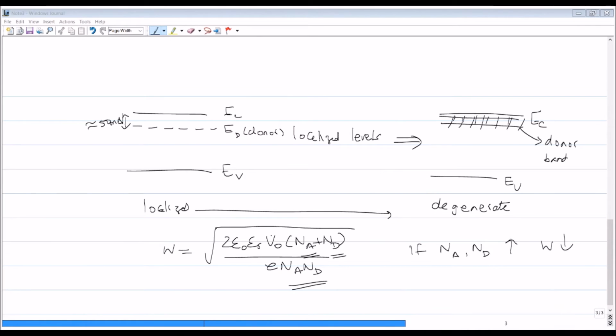Now to this semiconductor, let me add some dopants, let me add some donors. These are n-type. So we started off with p-type and now we are adding n-type, and this concentration is 5 times 10 to the 15. So it is more than Na. In this particular example, I have both acceptors and donors, so this is an example of compensation doping. Since I have more donors than acceptors, my electron concentration is Nd minus Na. So it's 5 minus 1 times 10 to the 15, that's 4 times 10 to the 15 per cm^3.